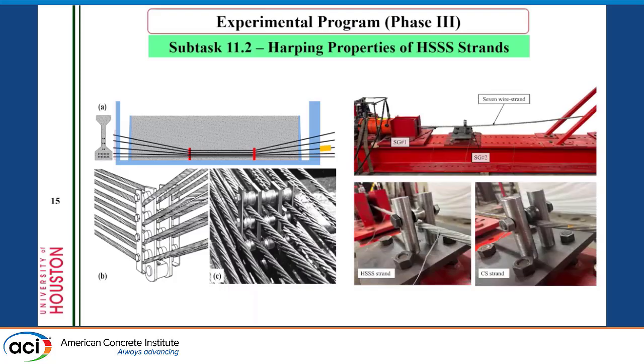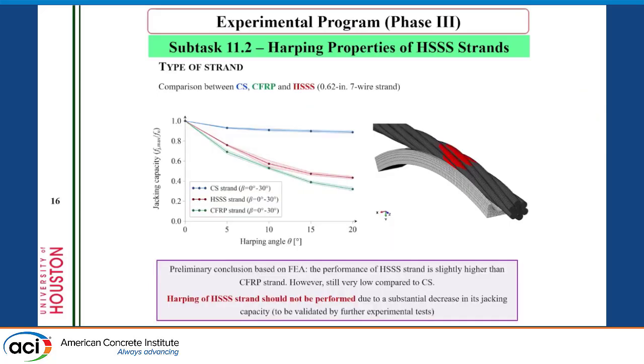So we already designed our test setup using conventional deviators that we have, either swivel or fixed. And that's our blind prediction before we tested. So basically, there is the CFRP, the stainless steel, and the conventional, regular carbon steel. Basically, we could harp at any angle. But for the stainless steel, we can see here that we cannot harp at certain angles, because we lost like 50 or 60% from the jacking capacity, which we get from the uniaxial testing.